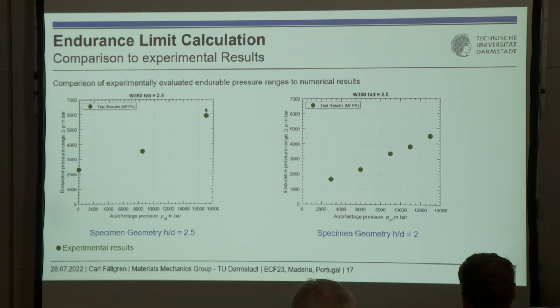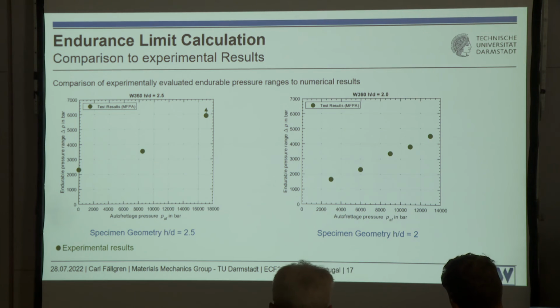So, what we see here now. On the left side, we see a graph for the thicker specimen, with a ratio of H to D of 2.5, and on the right side, we see it for the thinner specimen. On the x-axis in both graphs, you have the autofrettage pressure, which was applied to the components, and on the y-axis, you see the endurable pressure ranges. What we see here now in those green filled dots, those are the test results that we received from the MFPA,